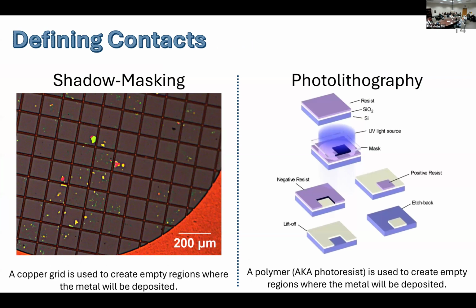Once we have our flakes on our substrate, we need to create regions that will eventually become the source and the drain contacts. We do this either by using the shadow masking method, in which we use the copper grid to create regions of empty space where metal is to be subsequently deposited. The other method we could use is photolithography, similar to the shadow masking method. Instead of a copper grid, we use the polymer, also known as a photoresist, to define the pattern, the regions that we want to open up for the metal to be deposited in.